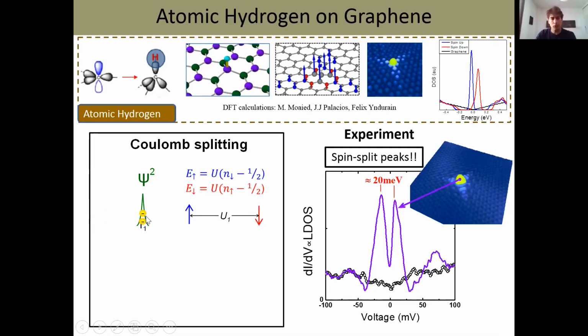If you want to put a second electron, you have to pay some energy because you will have electron-electron interactions, okay? So in a standard magnetic material, the magnetic orbitals are very localized. They have D or F orbitals, as in cobalt or iron, so they are localized to the atomic scales, let's say 1 angstrom. So the energy separation between these two states will be very large, of the order of electron volts. And here we are talking about 20 millielectron volts. That's almost 2 orders of magnitude less.